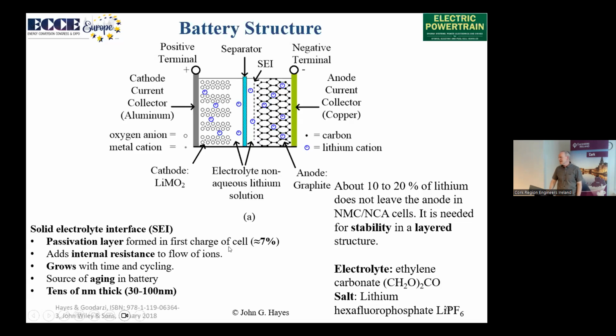And it takes about 7% of the total lithium that's going to be in the cathode. And it's kind of stuck there permanently. It's going to add resistance to the flow of ions. It's going to grow with time and cycling. It's a source of aging in the battery. And its thickness is about 30 to 100 nanometers thick. It's quite thin, but it has a fundamental role.